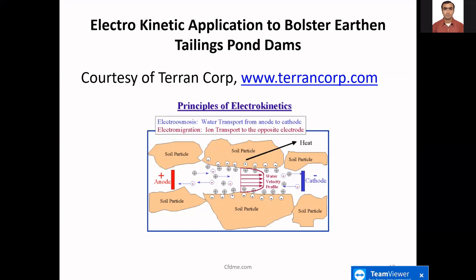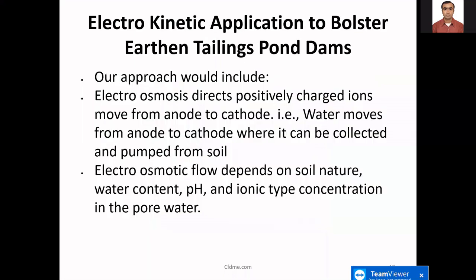And so we've got the transmission of the force applied at the anode, moving water towards the cathode. And as I said before, within Krishna's laboratory apparatus, you were able to collect that water and analyze the changes that occurred over time with the separation, if you will, of the positive cations and the anions. So it provides a means of limiting the leaching potential from the treated slimes.